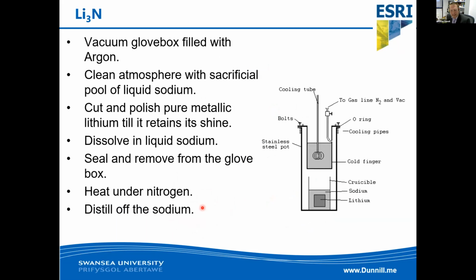So first of all, we have to make some lithium nitride in its purest possible form, which involves a vacuum glove box filled with argon. So we evacuate off this glove box overnight and then refill it with argon. We can clean the atmosphere within that box down to about 2 parts per million of water and oxygen by using a sacrificial pool of sodium. So this basically involves a large bowl of liquid sodium where you're scraping the top to get rid of the slag that forms on the top as it pulls all the oxygen and water out of the atmosphere.